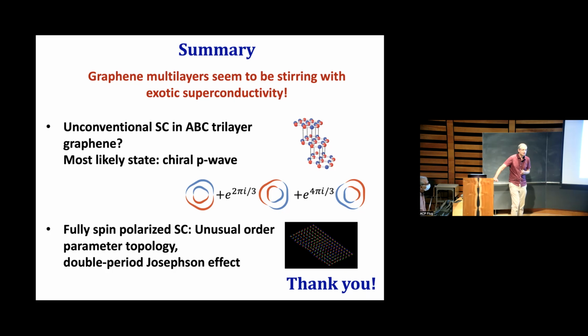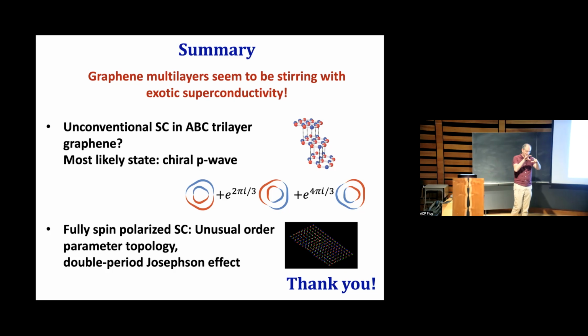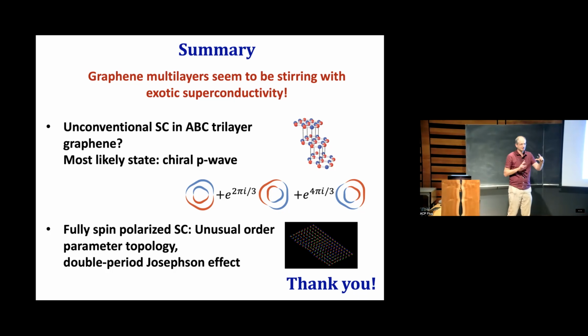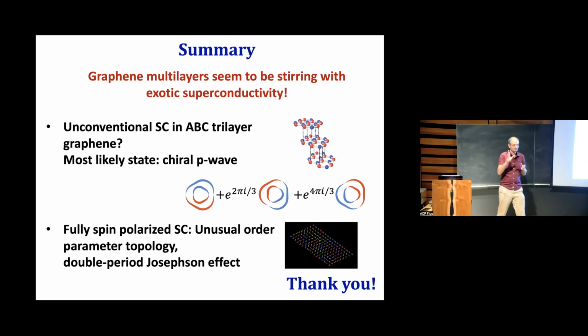So that actually depends on whether the spin is singlet or triplet. You can do a threefold rotation that preserves the value. So under threefold rotation, it looks like spin 1. It's a system with a triangular symmetry. So D wave and P wave are actually the same representation. The only distinction here is the spin. So relative to the center of the valley, it would look either like D wave or a P wave, depending on the spin.